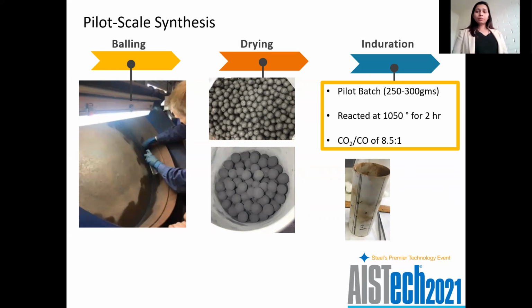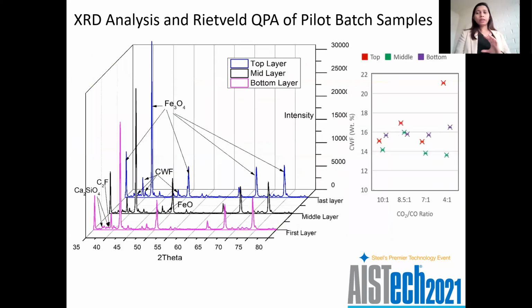Now, we did the experiments using these crucibles, which had holes on the side. This is before we made the holes. The height of the crucible is about 13 centimeters, and the hot zone of the furnace is about 10 centimeters, so we could fit about 250 to 300 grams of sample in every batch. Obviously there was a temperature distribution inside the crucible as well, plus minus 20 degrees. We conducted the experiments at different CO2 by CO ratios, and because of this temperature gradient, we decided to take 3 layers of the samples, top, middle, and bottom, and analyze them under XRD and SEM.